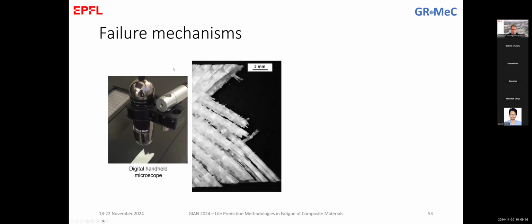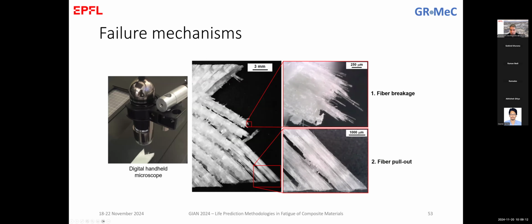So the observation of the failure at the end showed that we had mainly two fracture mechanisms that participated: the fiber breakage, which is the final failure, or the fiber pull-out. Fiber pull-out is when the fiber does not fail, but it goes out. So there is an interface failure between the fiber and the matrix. We did these observations with a very, very cheap digital handheld microscope. There's no need at this scale to use any expensive equipment.